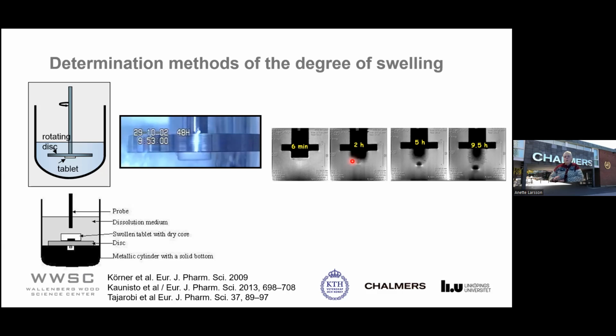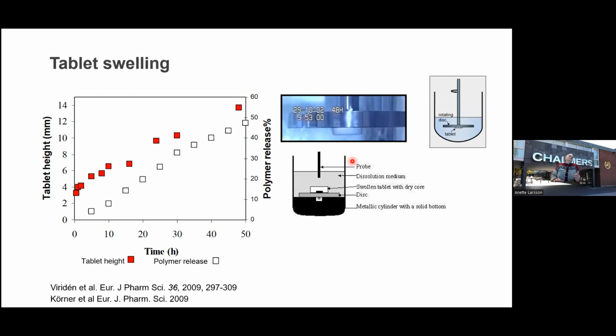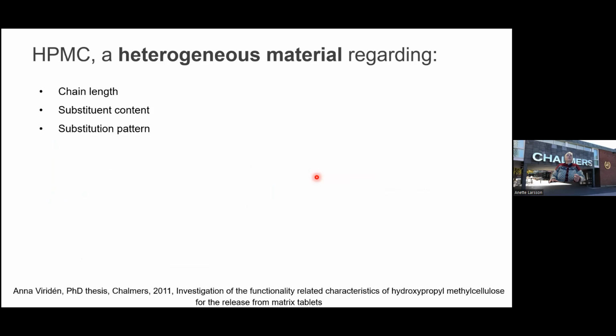So we did that, and we also developed simulation models to compare and also to check what is it actually that controls the release and drug release rates. Now, here is just an example where we have determined the position of the gel and also compared it to the drug release rate. And in this case, we use this simpler method, but still working very well, where we determine the height of the tablet.